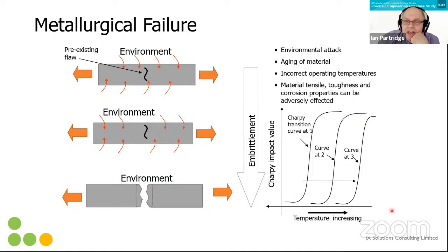the graph that I'm showing here is your Charpy transition curve. For those of you who do the Charpy test a number of times over different temperatures, for most steels, for most ferritic steels, you'll get a shape like this. And the material goes from being tough to being brittle. And what happens is if you get environmental embrittlement, you move this curve. So the temperature increases. So where before you needed to be maybe in a cryogenic application, you've moved it such that it could happen at room temperature, going from being very ductile to being very brittle. And again, you have some sort of pre-existing flaw or just a defect, and you've reduced the toughness so far that it just fails and overloads.